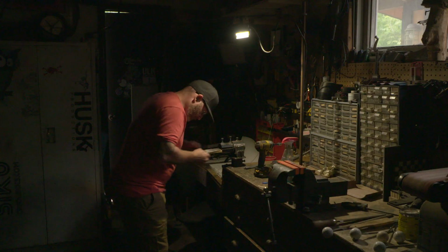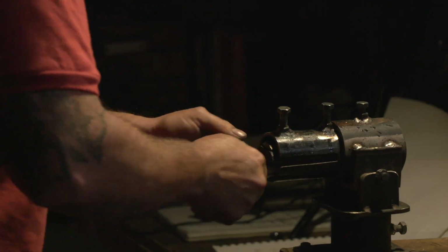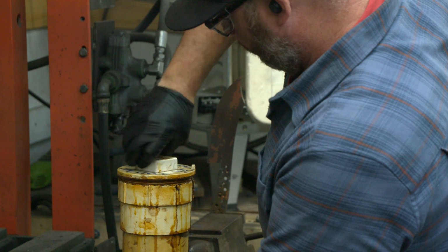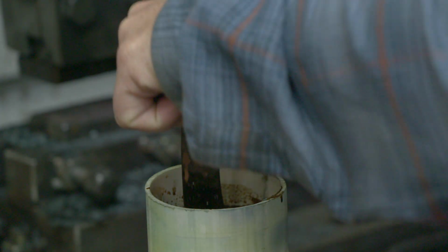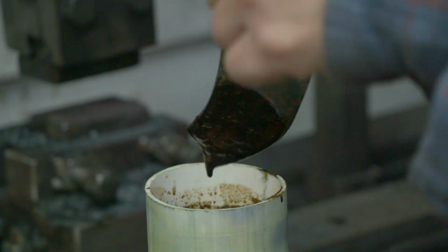Super stoked. After hand sanding, the knife is going to be etched in ferric chloride. Because the surface of the 1084 is consumed by the acid, the result is variations in layer heights, the 15N20 being proud. I want to go a little bit further with it. Coffee etch. I'm getting there, and it's looking great. The acidity of the coffee will stain the 1084, creating the most vivid contrast possible.